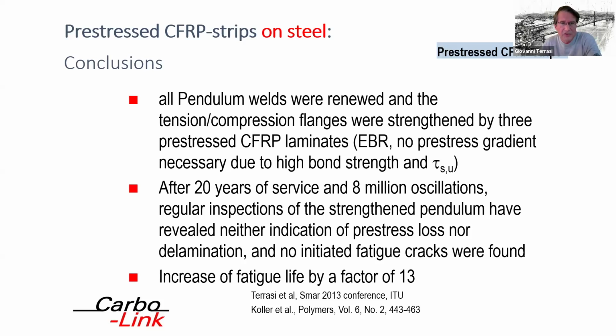And after 20 years of service and 8 million oscillations, our inspection showed that we had no fatigue cracks, no pre-stress losses, and no delamination. So we could increase the fatigue life by a factor of at least 13. And that was my short talk. Thank you very much for your attention and for questions then in the question session.